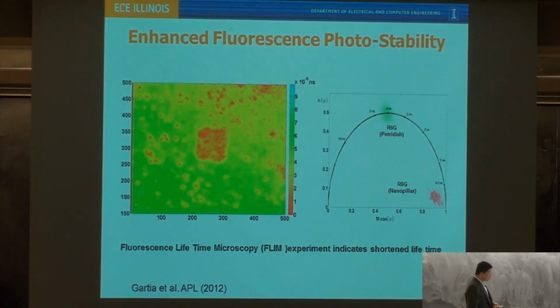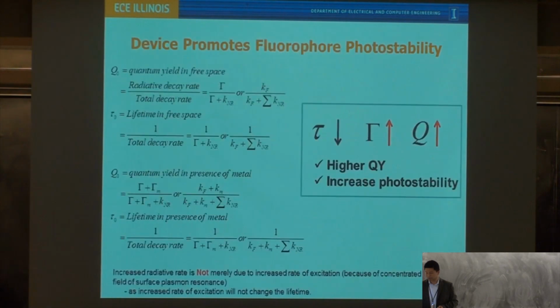So to respond, pose questions, and we also did the actual lifetime imaging by collaborating with Bob Clegg, using his system to categorize the fluorescence lifetime on the surface. We find the lifetime for this particular dye, rhodamine 6G, on the petri dish and on these nanostructures becomes very, very different. Basically, we shorten that lifetime significantly, which potentially can improve the photostability of this dye many fold.